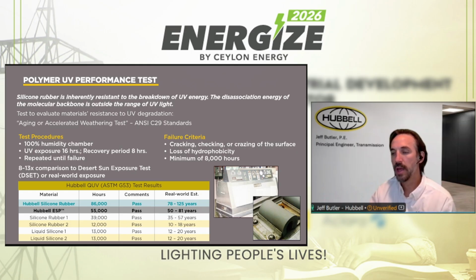exceeded the others. But the other interesting note was the difference between silicone rubber 1 and silicone rubber 2, which should have been similarly qualified, similar performance polymers, and yet we saw a dramatic difference in the performance of those two rubbers. So it just speaks to, even though a silicone rubber may be commercially available, may be manufactured by a given company, there could be dramatic differences in the performance of those materials, and that needs to be investigated.